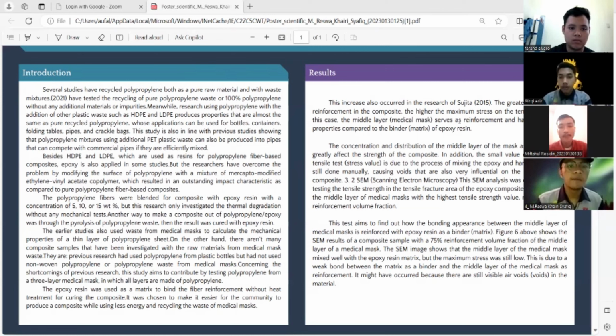The polypropylene fiber was blended with composite with epoxy resin with a concentration of 5, 10, or 15%. But this research only investigated the thermal degradation without any mechanical test. Another way to make a composite out of polypropylene and epoxy was through the pyrolysis of polypropylene waste. Then the result was cured with epoxy resin. The earlier study also used waste from medical masks to calculate the mechanical properties of a thin layer of polypropylene